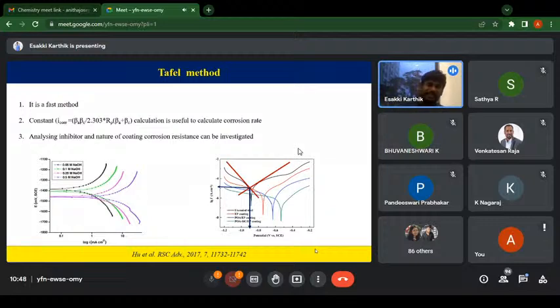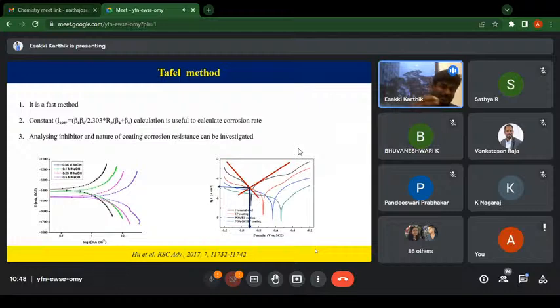Once you know the corrosion potential, it tells about the thermodynamics of your corrosion process. If the corrosion potential is moving towards the positive side, see here in my left side graph, 0.05 molar NaOH is slightly more positive than 0.5 molar NaOH. Approximately it is about minus 1430, 1450 for 0.05. But when you go to 0.5 molar NaOH, it is nearly 1490.